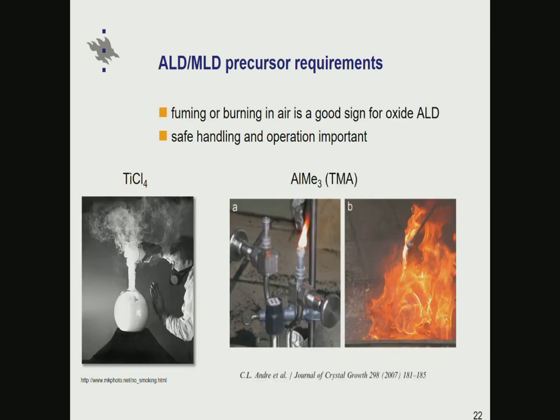Christoph already showed you what happened with these alkyl compounds when exposed to air. So this is TMA leaking out from the cylinder. This is probably where somebody has tried to add water on top, so that's not a good idea. Christoph didn't say what to do when fire breaks out, so you should use sand or some vermiculite or other materials which are not reactive, and just prevent oxygen and moisture vapor getting in contact with these precursors.